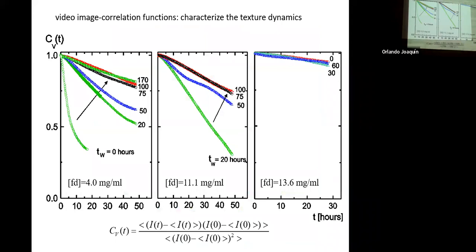The way to do this is to construct an image time correlation function. You have a CCD camera with hundreds of pixels. You measure the intensity of a pixel at time t, subtract the average over the whole chip, then multiply that by the intensity at t=0 minus the same average for intensity over the entire chip at time t=0, and normalize it to 1 at t=0. Then you average over all the pixels, and you get what we call video image time correlation functions.